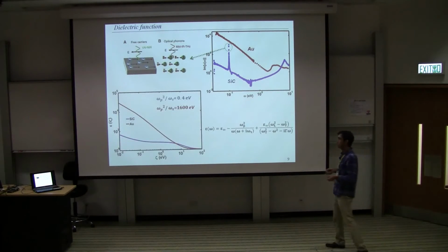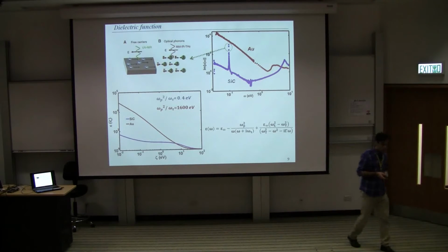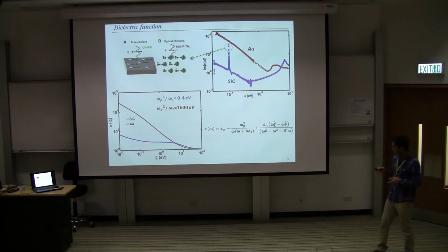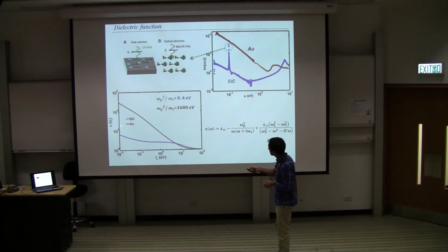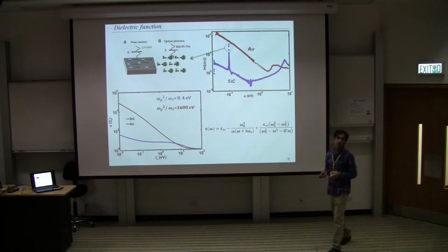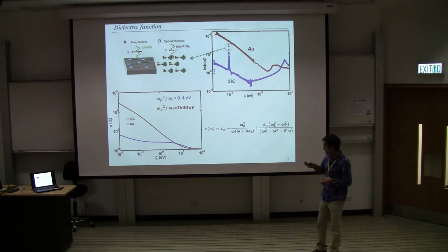By using the Drude model, which corresponds to the charge carriers, we extrapolated the dielectric function to the large frequency domain, which we need in the imaginary part to calculate the Casimir force via Lifshitz theory.